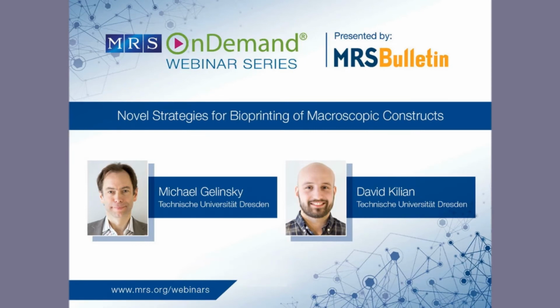So basically those are approached via strategies that we just saw, so modifying the procedures, optimizing the bioinks and procedures to make the process less harsh basically for the cells. However, if we speak about cells that die due to the lack of oxygen or nutrients inside the volumetric structure after some time, it's basically about the limit of diffusion of those factors inside the volumetric structure. So there's certainly studies out there showing that in the middle or the central area of the strand, there's sometimes a lower number of viable cells compared to the peripheral structures.